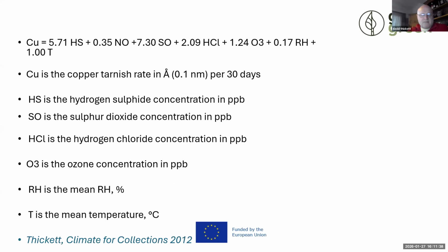Just an example of an indoor damage function. There aren't many of these. There are lots of outdoor ones. This is one I was involved in developing, and we measured the copper corrosion rate at 6 sites over 3 years. They were naturally ventilated, so at periods that were very different, relative humidities, temperatures, and all those gas levels.